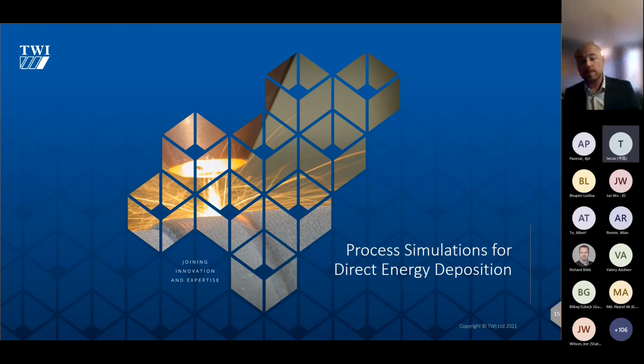And just to give a similar example on nickel-based superalloys for direct energy deposition, powder bed fusion is lovely. It creates nice intricate parts, but you're limited by your build chamber size. Whereas with direct energy deposition, it's open architecture. We can just deposit material, move along a path. We might not be able to have the geometric freedom that we have with powder bed fusion, but we can build much bigger scale engineering parts.